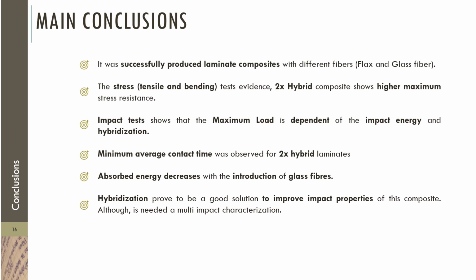We can also conclude that the impact tests present a maximum load dependence on the impact energy and hybridization. The minimum average contact time was always observed for 2x hybrid laminates, and the absorbed energy decreases with the introduction of glass fibers, which means that our composites present a higher stiffness for 2x hybrid laminates.